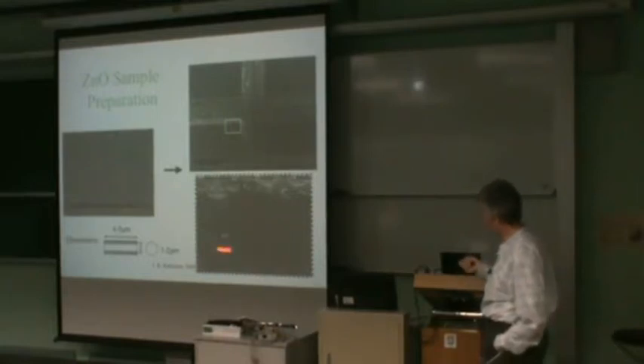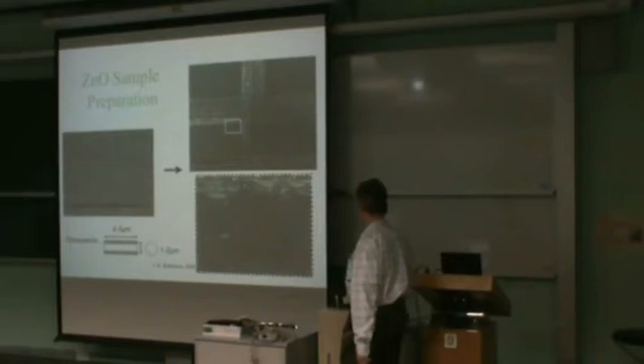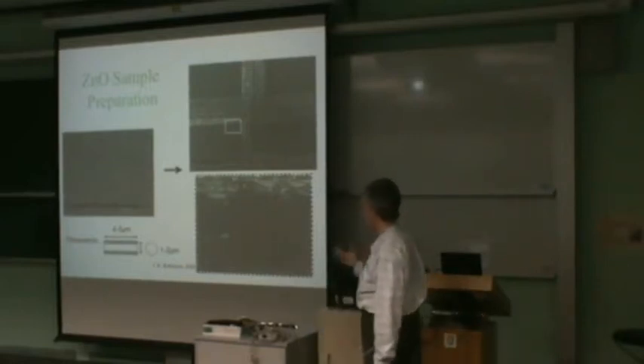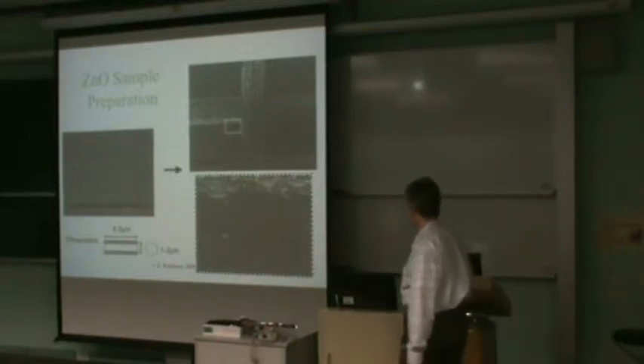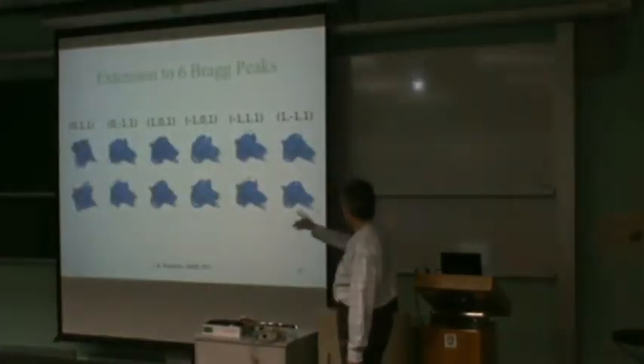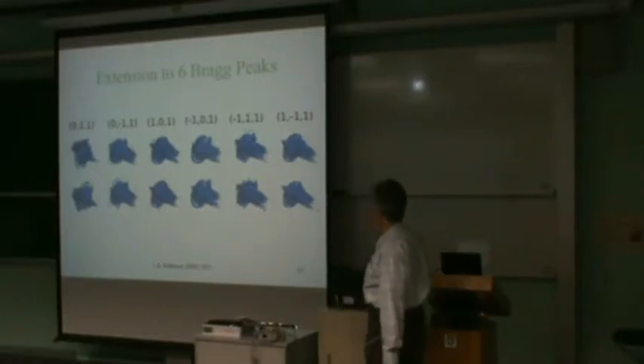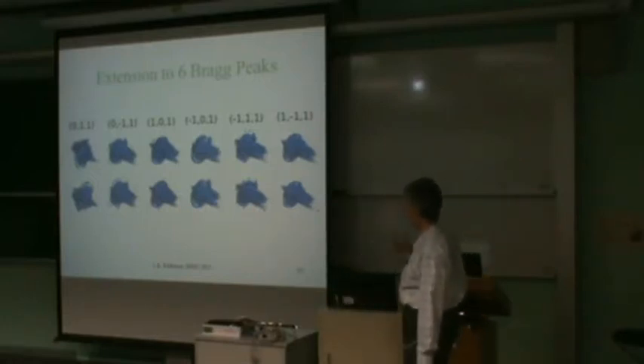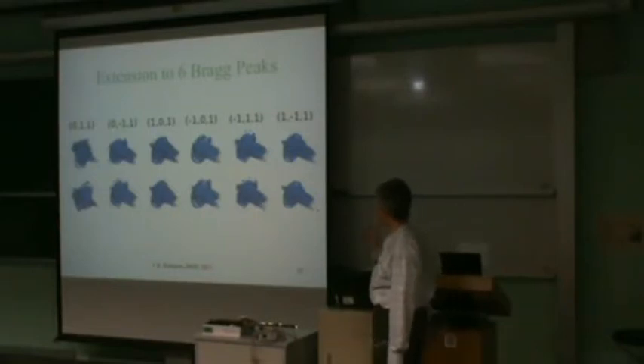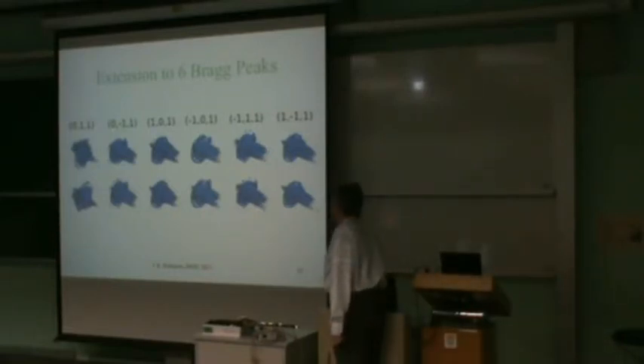So what we did was use the fact that we can control the position of the X-ray beam to measure the diffraction pattern of this, but because it's isolated, we can turn it around and measure several different Bragg peaks all from the same wire. And so here the exercise is to measure the strain in all its different projections and get a full 3-dimensional image of the strain field. So here are the 6 Bragg peaks we measured, and those are the diffraction patterns that correspond to the 6 Bragg peaks. They all look pretty similar, but there are small differences between them that correspond to the strains.